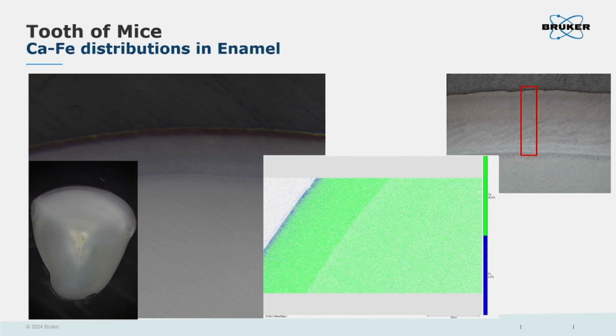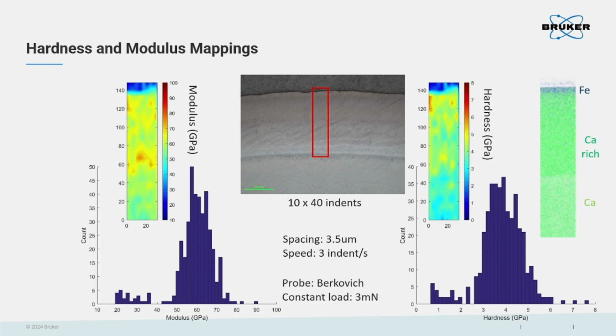Before we have the indentation results, we also have the information of the chemical composition measurements. So we can see there are two elements. One is calcium, marked by green color, and the other one is iron, marked by the blue color. If we take a look at this distribution of chemical elements, we can find an interesting distribution. On the very top of the enamel, there is a very thin top layer that is iron rich, and then we have a calcium-rich region in the middle, and then at the very base and the bottom region we have the fully